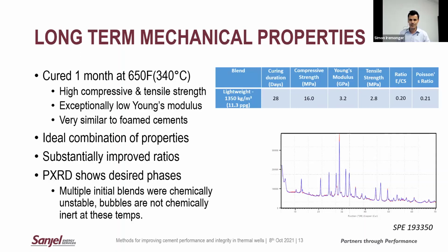There's a question about talking about failures. I do want to talk about the failures we had here. This was not an easy project. We went into it kind of assuming that things would be relatively straightforward. It took a number of iterations of blend design to actually get workable slurries that were stable at high temperature. And the assumption that these glass microbubbles are inert certainly does not hold true when you're dealing with temperatures of 340 degrees Celsius, a couple of thousand PSI confining pressure, and highly caustic conditions in your cement, like pH 13. Under those conditions, there's not many materials that are chemically inert, and that's certainly what we saw. And it took a number of iterations and optimizations and collaborating with the manufacturer to get a system that was thermally stable, long-term, and robust. So, yeah, everyone likes to talk about our successes, but this one was a tough nut to crack for sure.